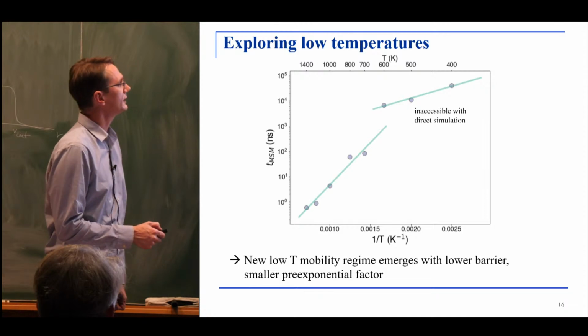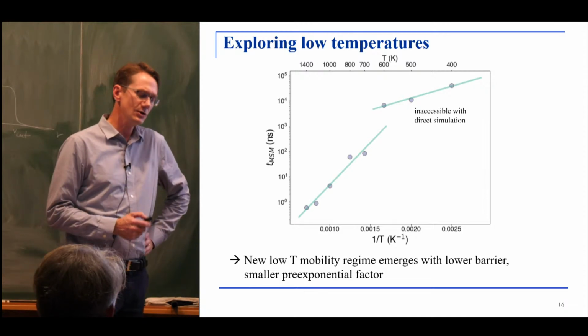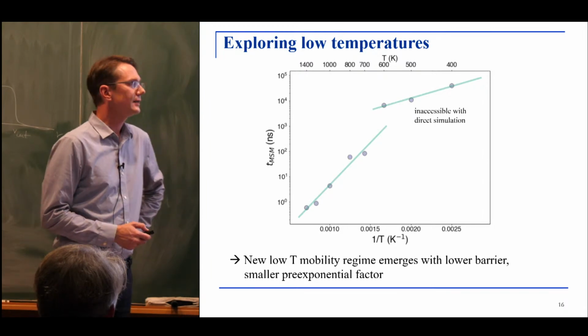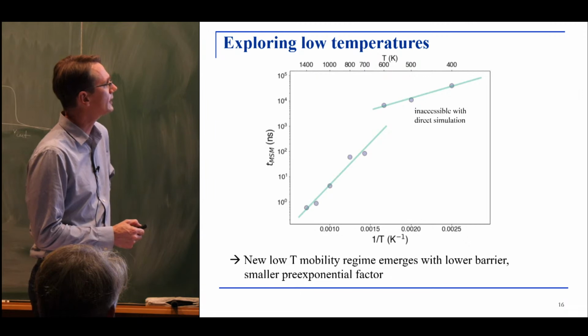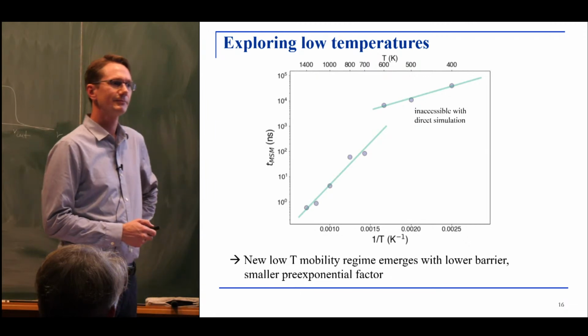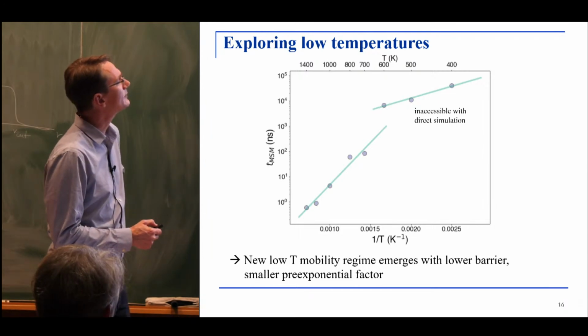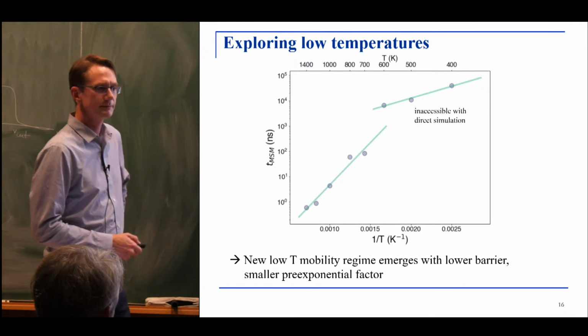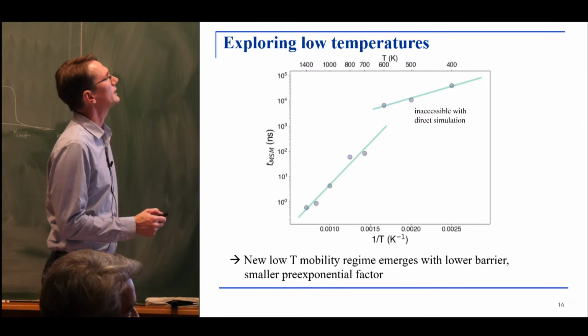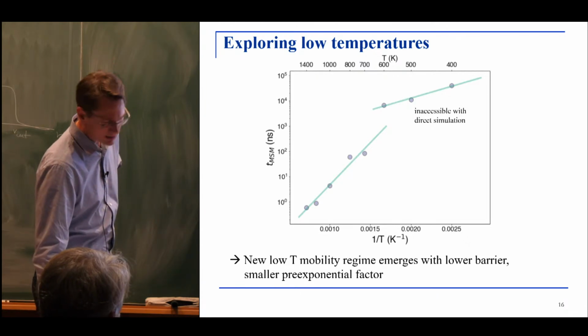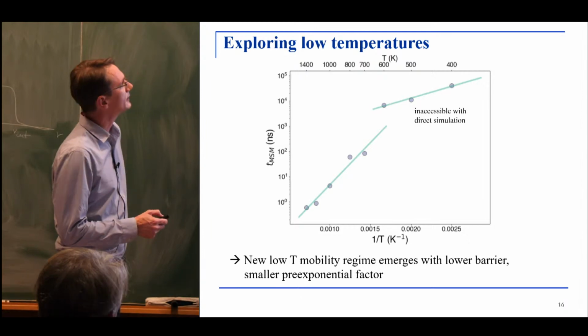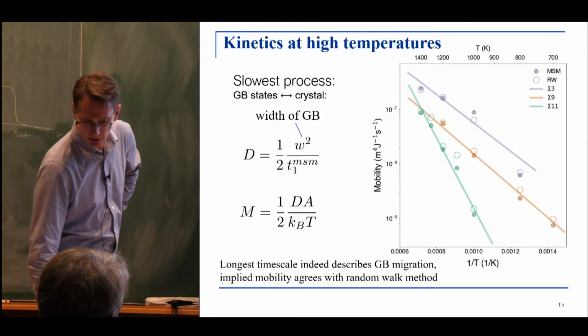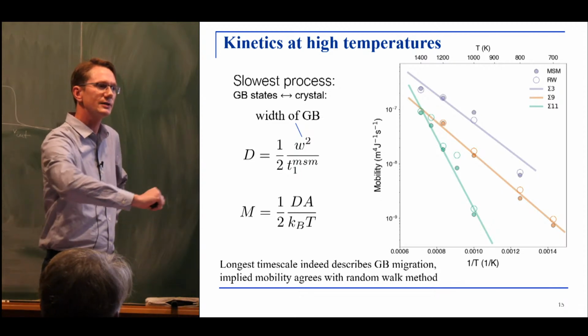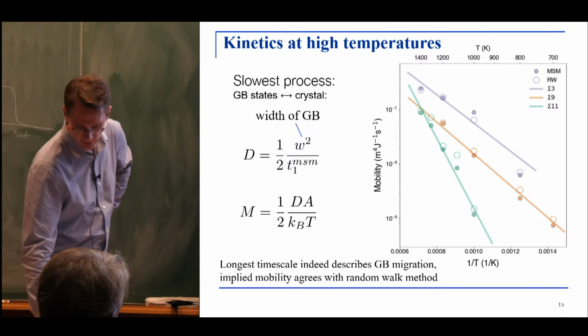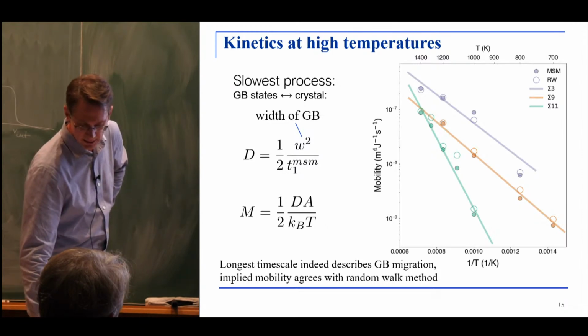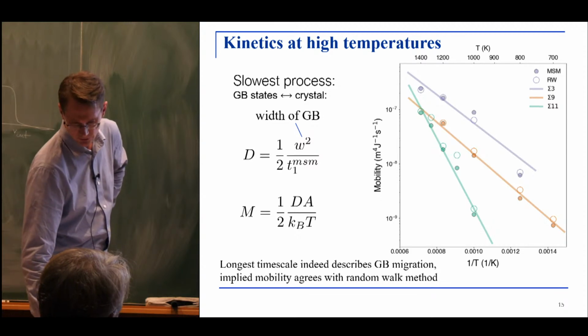Okay, good question. So it turns out that it does not really matter. We've checked different temperatures, and it turns out that you can learn at one temperature and apply at other temperatures. Well, but not on the top 3, right? Yeah, well, even there we get a good agreement. So they are not accessible with direct simulation. Okay, so we were able to train the model in this temperature regime, but we are not able to calculate the mobility using the direct brute force MD method. You need much more statistics. That's exactly right. So we can obtain the time scale, but we cannot do this direct calculation anymore. That's right. All right.